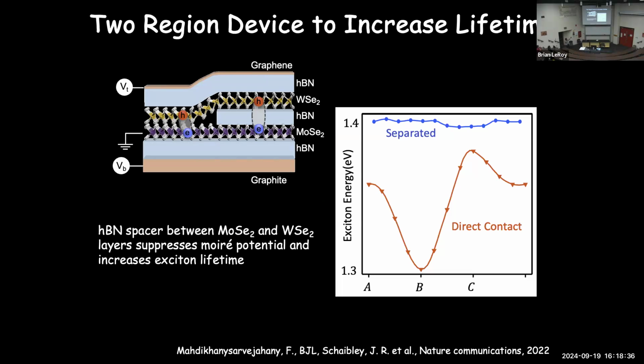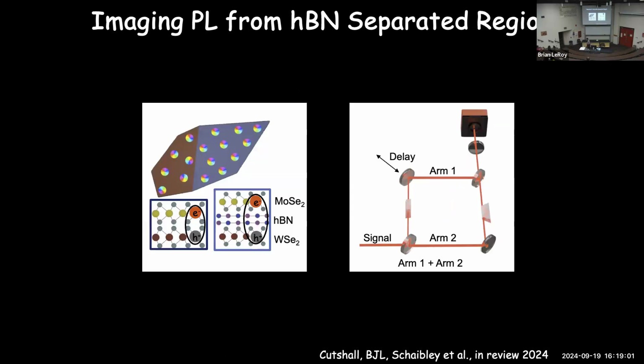And the reason I want to increase the lifetime of this state is I want to make a lot of these particles. Because if I can make a lot of them, I can make them into a condensed state and into a superfluid. Basically what I'm trying to do is create a superfluid of these excitons, these charge neutral particles, by making them extremely long-lived. I only have maybe a couple minutes to go into this, so I'll probably have to skip most of the details, but I hopefully can just show you quickly the results here.